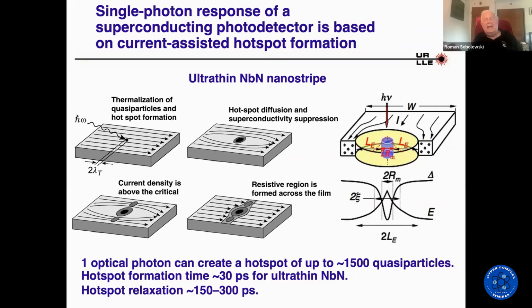And obviously, if I have a bulk piece of a superconductor, the local photon perturbation will be small unless the number of photons is very large. But if I have an extremely narrow, thin stripe, on the order of a few nanometers, and I bias this stripe with current, even a single photon may create a large enough perturbation to push the current outside, and this way reach the critical current and create essentially a resistive barrier. So again, we switch from the zero voltage state into the resistive state.